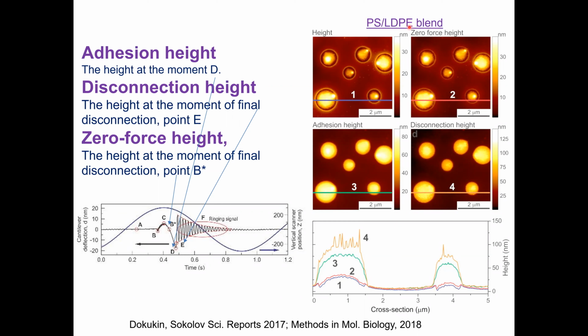And this is, for example, a polystyrene, low density polyethylene blend, this classical sample for calibration of your mechanics, provided by Bruker. And you can see what happens with low density polyethylene. You can clearly see the difference between a regular height and its zero force height, pretty big adhesion height and quite large, even almost noisy disconnection height. Disconnection is the moment the last molecule was disconnected from the sample surface. First you can think it's noise, but if you really look at the pictures, you can see these are actually patchy.